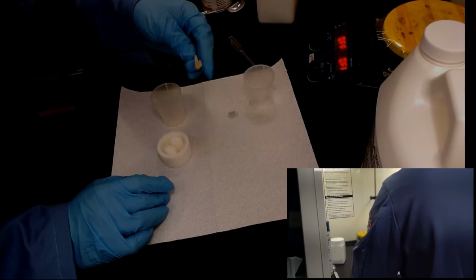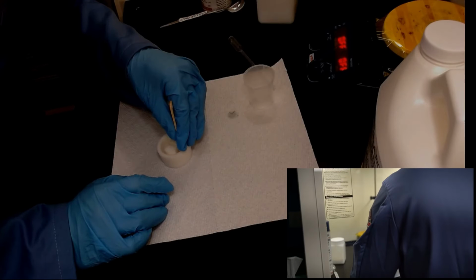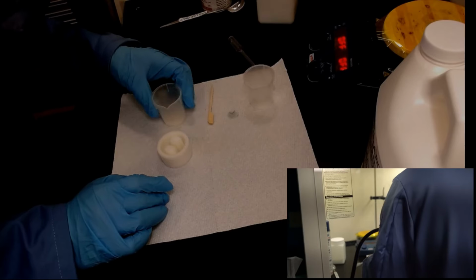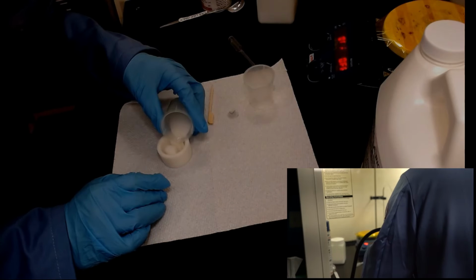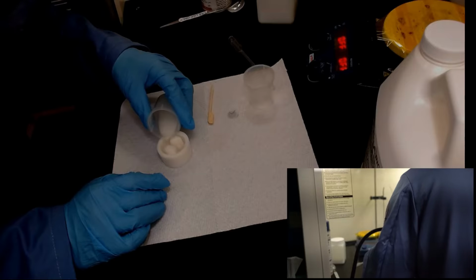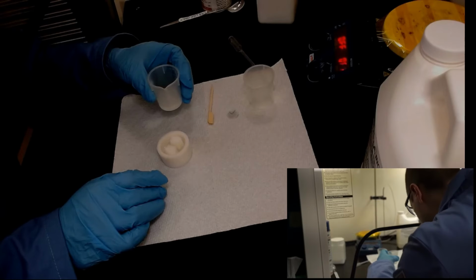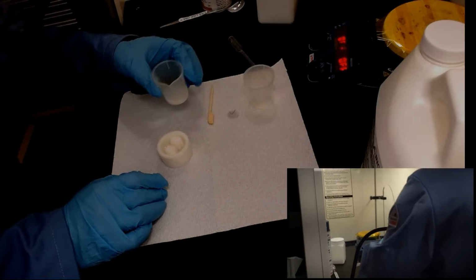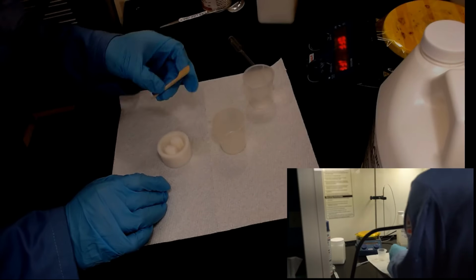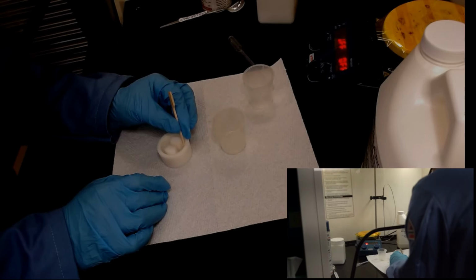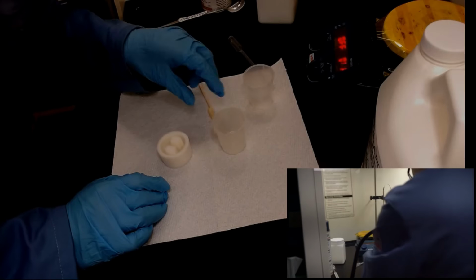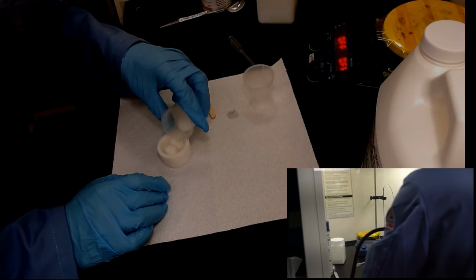So in this case, we're trying to get the sample buried about 6 millimeters of total depth. That's about the right height for the sample holder that I'm using. If you go too deep, it just means you have to polish off more material afterwards, and it's a waste of time and abrasives. And then I did get one little air bubble there, so I'm just going to pop it real quick with a toothpick so we don't get a void in the mold.